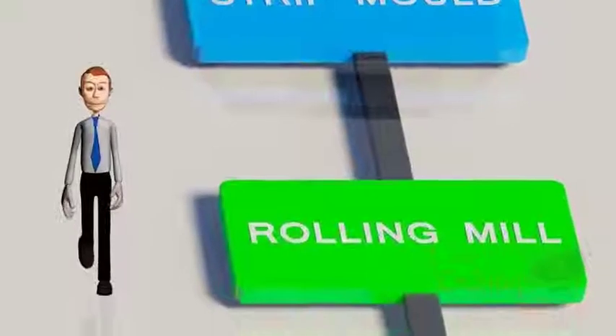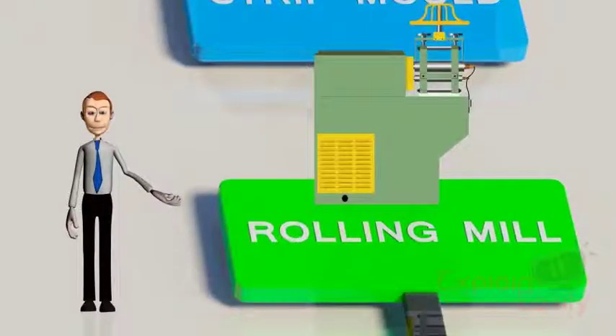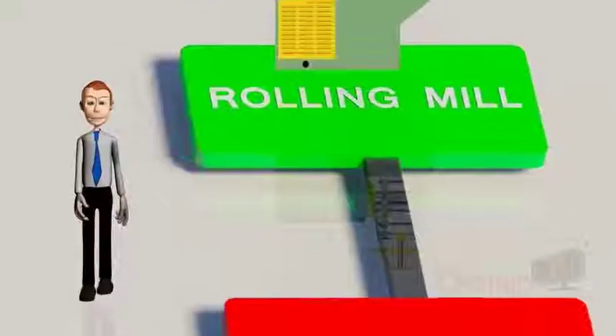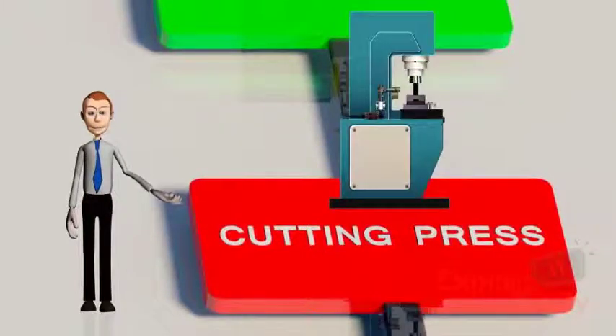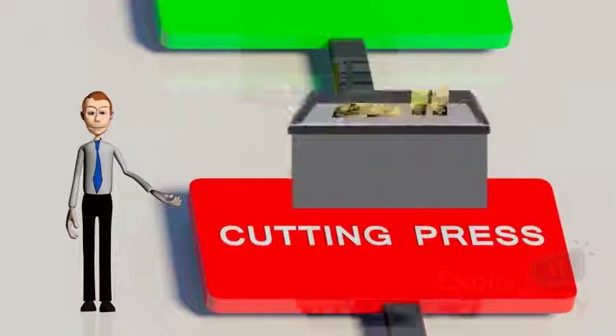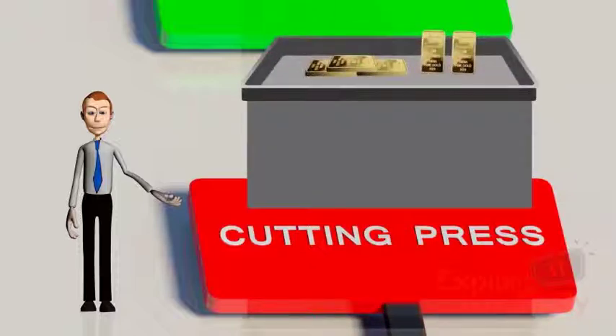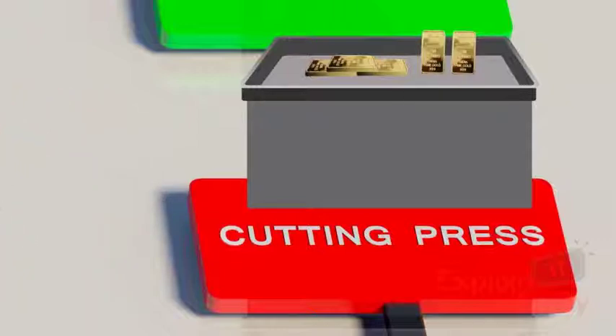These gold strips are then passed through the rolling mill, where the rollers are set to get the right thickness of the strips getting converted to sheets. These sheets are then passed through the cutting press with set of punchings so that gold blocks are cut as desired. These gold blocks are then annealed to remove oxides by a flame and then cooled and cleaned. The shining gold bar is then put on the stamping press to number and configure the desired mark or logo.